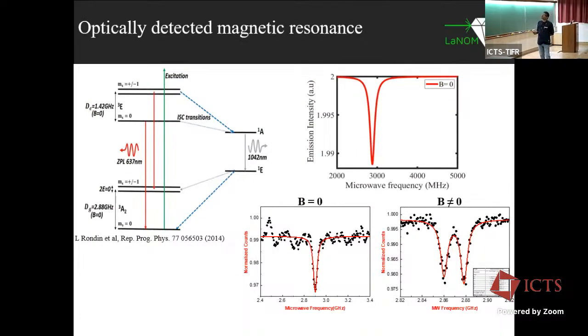Recently, we were successful in developing optically detected magnetic resonance. And thanks to Fani for all his help, we were struggling to set it up. As we go back to the basic energy level diagram, you can lift the population, and it can come back by spin conserved or spin selective transitions. Then you apply a microwave, you lift the population between these two, since this becomes the dark state, and you see a dip in the fluorescence intensity.